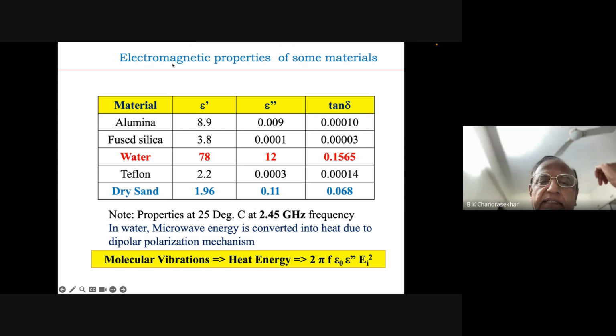Let us look at water. Water has an epsilon prime of 78, which is very high, and an epsilon double prime of 12, which is also very high. So therefore, water is a very good absorber of microwave energy. The reason is water is a polar liquid. It has orientational dipoles already present, so it can oscillate under the influence of an electric field. Therefore, at very high frequencies, it becomes an absorber.